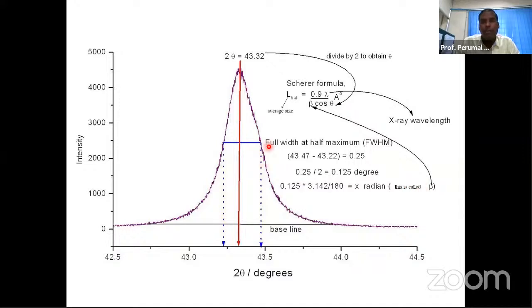Then what is FWHM or full width at half maximum? So this is zero intensity, this is maximum intensity. Half is somewhere here. You take the half intensity here. Take the difference, and you get the width in degrees. That degree must be converted into radians by multiplying by 3.142 and dividing by 180. That is your full width at half maximum. Already you know lambda and the 0.9 is there. Theta you are getting from here. And beta now you are getting, that is the full width at half maximum, FWHM. All quantities now you have and you can estimate the Scherrer grain size or average grain size.